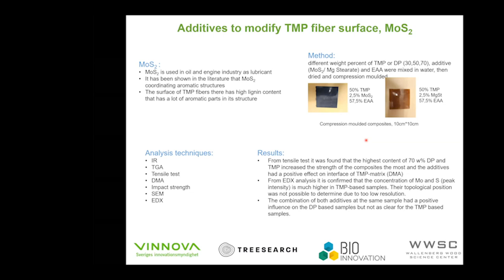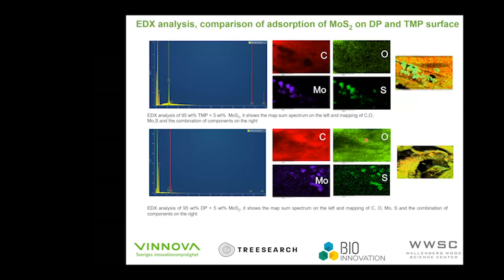And at the end, we said, why don't we use a combination of both additives, magnesium stearate and molybdenum disulfide, in the samples. It was interesting that we had a very positive effect on the DP-based biocomposites. We had a positive effect on the TMP ones also, and better mechanical properties, but it wasn't as much compared to DP. So here you can see the EDX analysis.